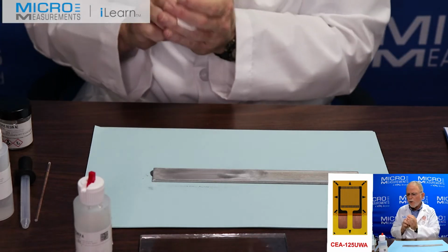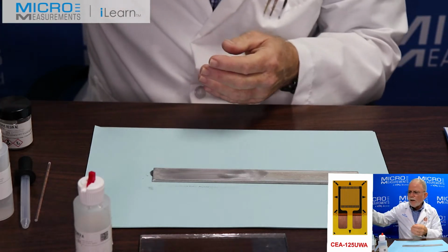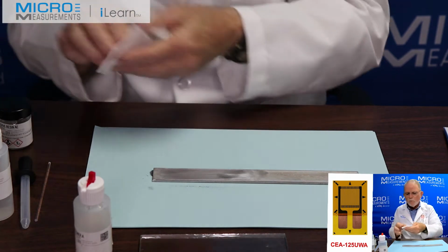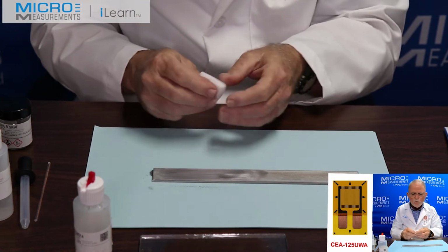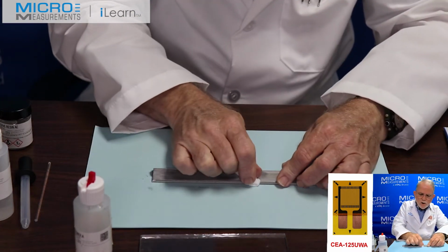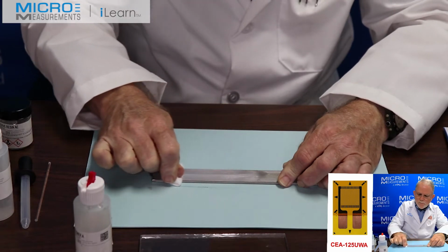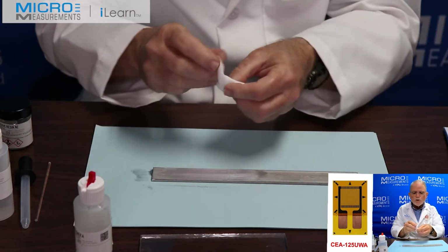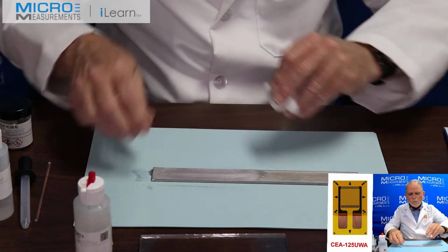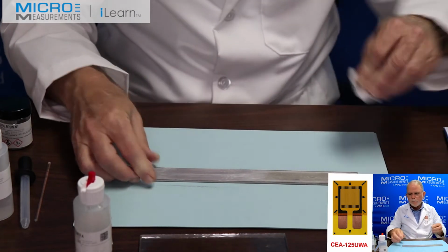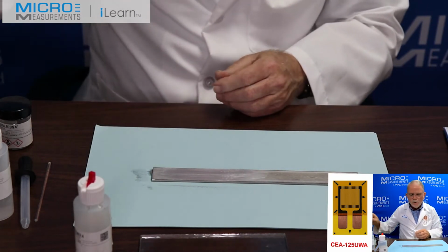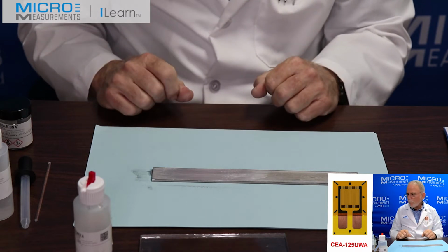Having completed that operation, I'll take a clean, dry gauze sponge and with a single wiping motion absorb the contaminated material off of my beam. It's important to use a single wiping motion. If you wipe back and forth, you'll recontaminate the area. Okay, we've now wet abraded with the 320.